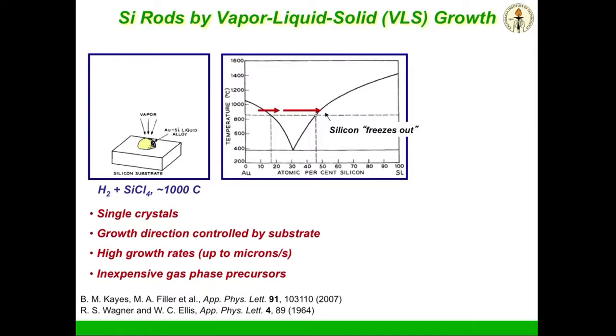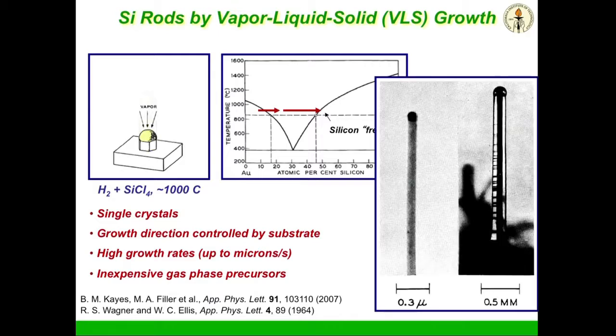And then it has only one place to precipitate, and that's at the phase boundary between that alloy and a crystalline silicon substrate. And because that's the only place it can precipitate, it will be like growing seeds of corn into stalks of corn, and the molten catalytic drop will ride along the top of that growing crystallite of silicon until you stop feeding it precursor. Now, this is an example of a 1964 first paper of this, and that scale bar is 0.5 millimeter, showing the single crystal of silicon grown by this vapor liquid solid growth method.